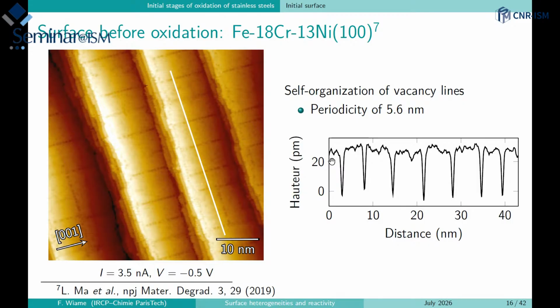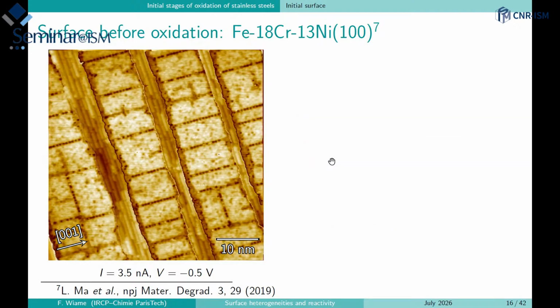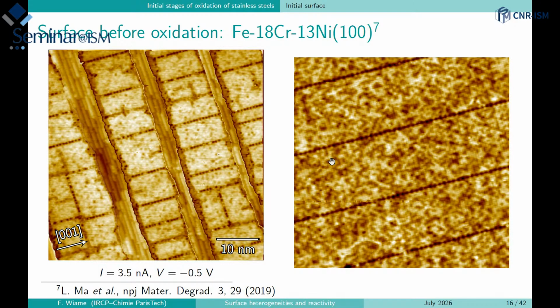If we want to look more clearly at what's happening on the terraces, I leveled out all the planes just to show you here. So this is the same image where I just leveled out all the planes to see better the contrast on the terraces. And you can see that we can clearly see now the atomic resolution at the surface. So each dot is corresponding to one atom at the surface.